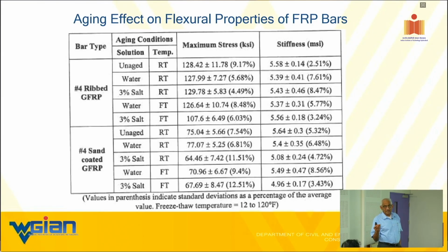Keep that in mind, okay? Because when we pull through the bar, it may be cured 80, 85% or whatever that number, somewhere around plus or minus 80%. I still have a few ways to go to reach my 98%, 99% thing. So that comes with the aging of the material.